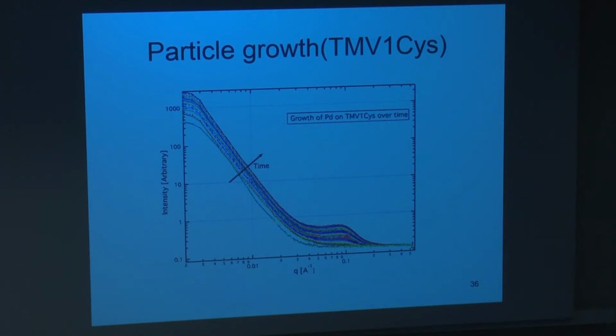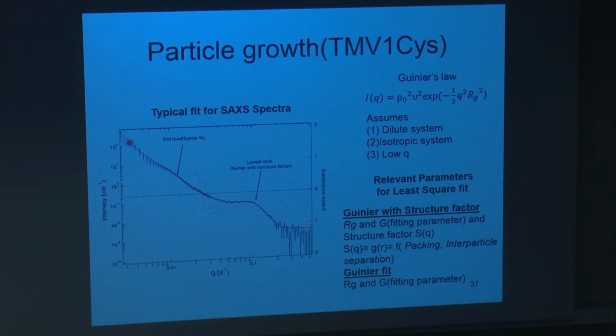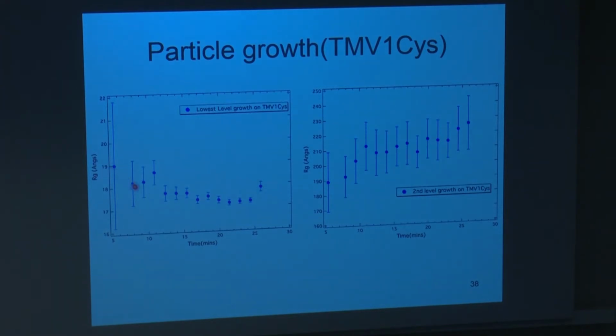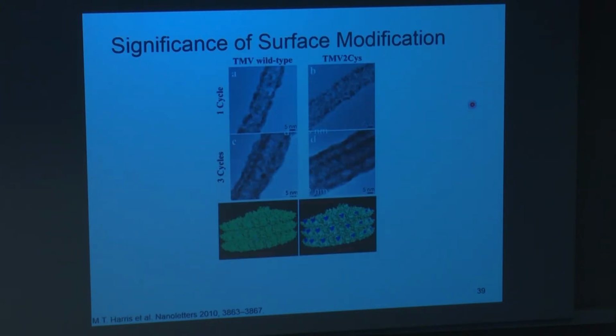especially if you look down here, where you have a nice Guinier region, so that you can get the size of the particle, and model that, and this is Mayo's work that he used to model the data. There's like a second level Guinier region. Exactly what those particles are, I couldn't tell you, but the small particles are probably the very small particles that we see on the surface of the TMV. There's also some question, well, could these also be the pore spaces between the particles? But I think it's probably the very small particles that are on the surface of the TMV. But this second level growth, we haven't figured out exactly what that is.